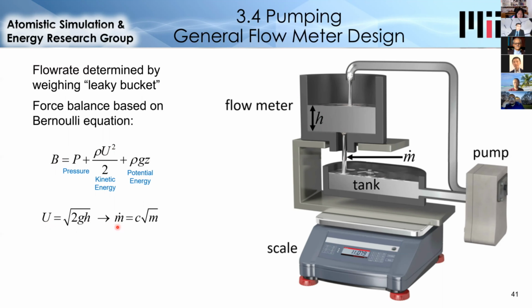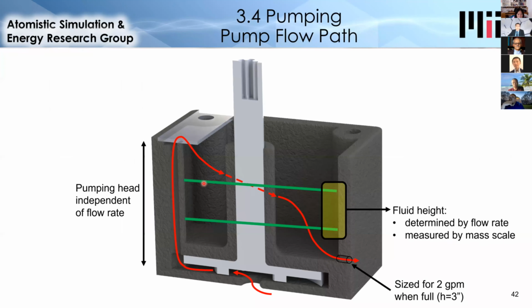And we find this relationship where the mass flow rate is equal to a constant times the square root of the mass of the tank, because the mass and the height of the tank are related. So with this relationship, we can measure the weight of this tank and determine the flow rate. To further simplify the system and reduce heat loss, I made the pump and the flow meter a single component. So you see here in light gray is the impeller that rotates. The fluid comes in, is slung outward by the impeller, and flows through this path to the top of the pump, and then falls into the container on the top of the pump.